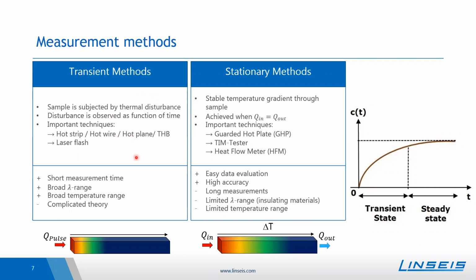The transient measurement methods, because they already have a look when the sample temperature is changing, are rather fast. So typically the measurement times are in the range of some seconds or lower minutes. And the most common techniques which belong to the transient group are the hot strip, hot wire, hot plane, or transient hot bridge method, as well as the well-known laser flash method. These are all transient measurement methods.